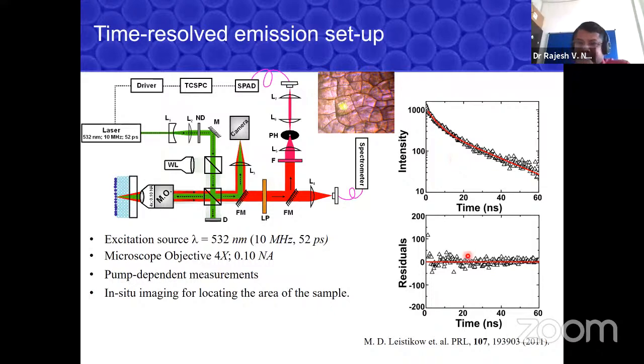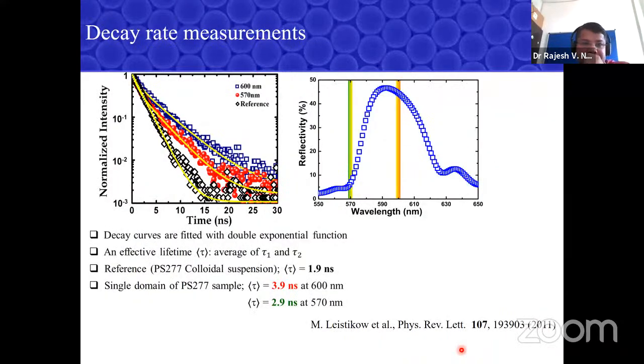The residual shows that once you fit the curve with the appropriate decay function, single exponential, double exponential, or stretched exponential, the choice is yours, whichever best explains your data. We followed a double exponential fit, following this work in Physical Review Letters, where it gives a convincing lifetime for us. So we did these measurements. This is a typical lifetime we measure from the gap. Here the spontaneous emission intensity is plotted as a function of time. The black one is a reference decay of the dye suspension used in the sample, which shows a typical lifetime of 1.9 nanoseconds.